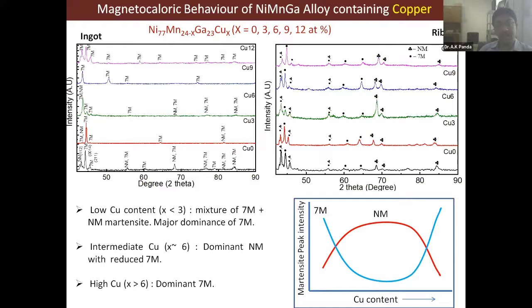And this is the basic idea: you can work with your alloy chemistry to change the martensite content, because this is related to your magnetostructural coupling. If you are able to modify the martensite, the variations of the martensite and the intermartensitic, I mean the changes within the martensitic group, like going from 5M to 7M, 7M to 14M, or even via non-modulated martensites, then you can modify the structural phase of the material.